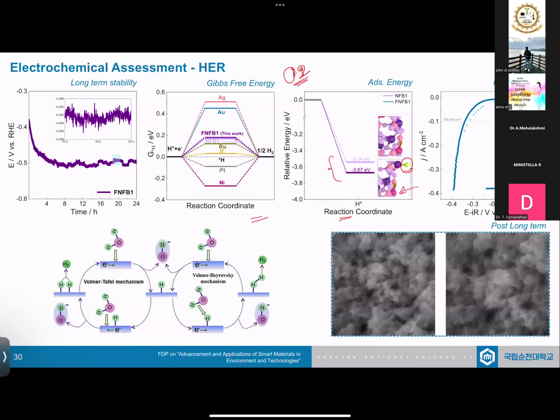And it is very good because we know the best material for the hydrogen evolution reaction is platinum, which is minus 0.09 electron volt, which is very close. It's still not great, but just one atom itself is substantially improving the activity, at least bringing it as close as possible, making the mechanism much better. I'm not going deeper into the mechanism as I'm losing much time over here.